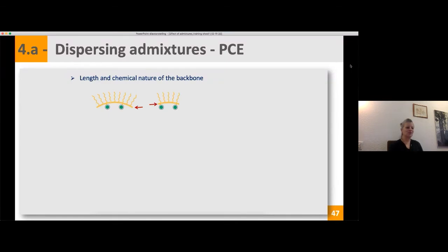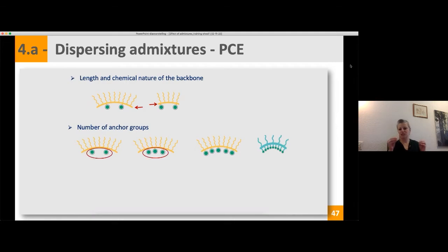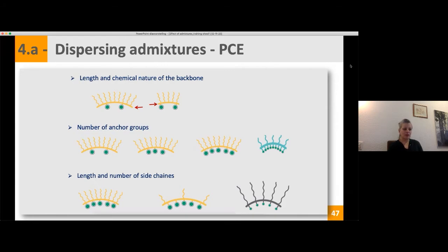I said a bit also, but there are so many ways you can work with your PCE. You can play with the length and the chemical nature of your backbone. You can also play with the number of anchor groups, which means with the charge density. So depending on the composition and the specification of your cement, how much aluminate there is, and the charges, you can target which type of PCE is best for this type of material. And then you can also play with the length and number of the side chains that you have. So you can have short chains, you can have long chains. You can also imagine that if you have short chains, the dispersion will be smaller than if you have a large chain.